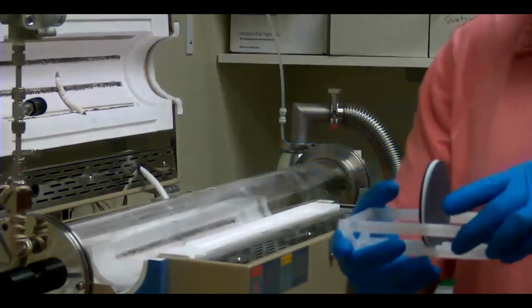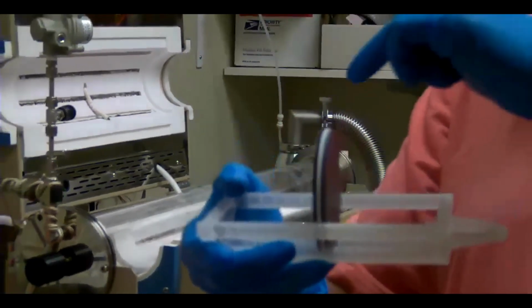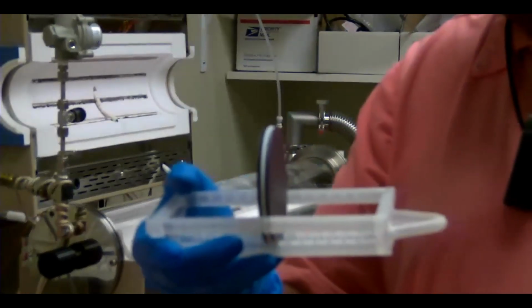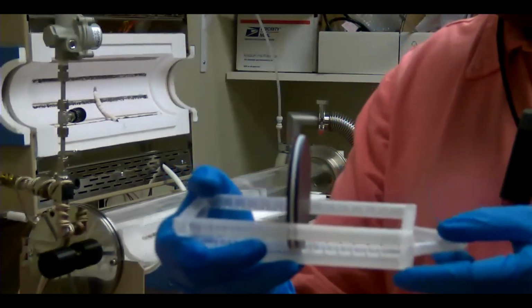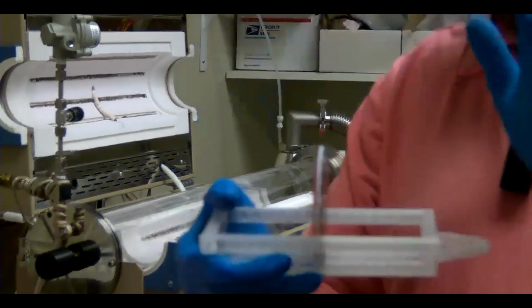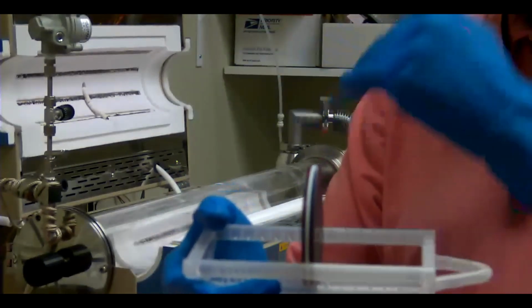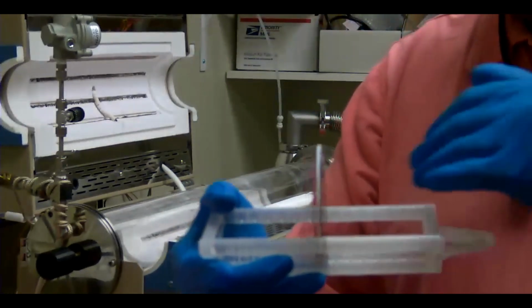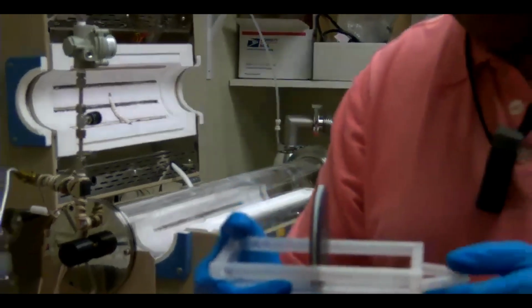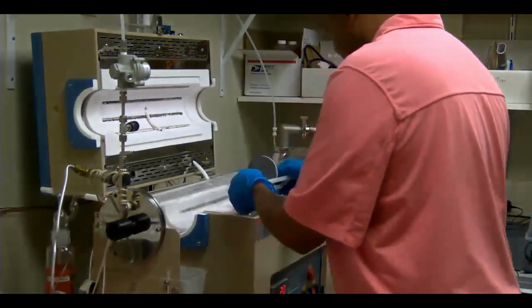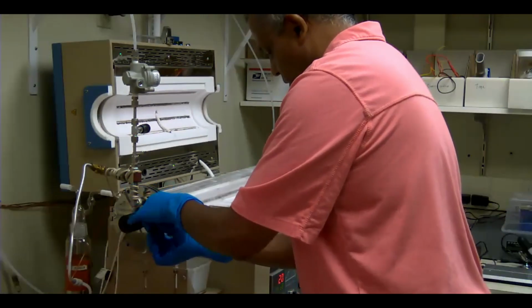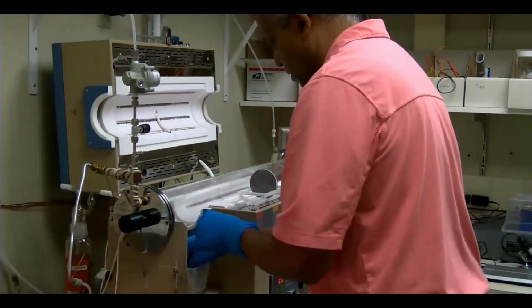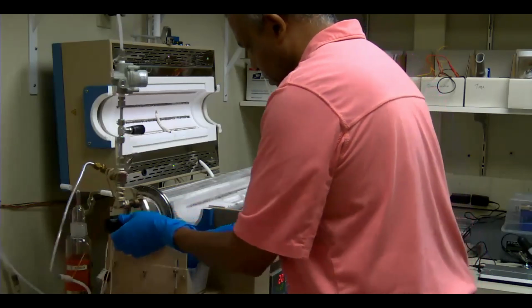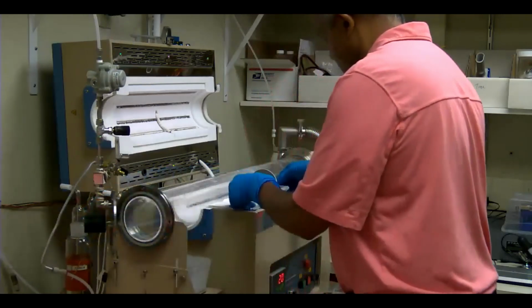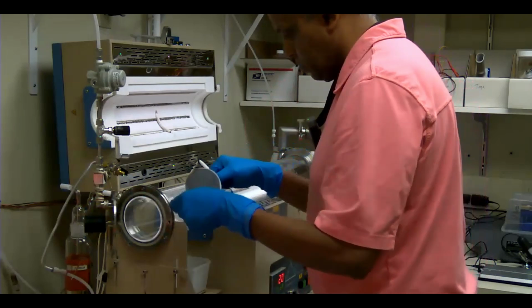Here is the structure. We have the ceramic that contains the boron oxide in the middle, silicon on either side. The doping side is facing the boron, and this is the back side, which we are not doping, but we will have to dope that too later because that's an N-type substrate. We're going to run this at atmospheric pressure, but not with air. I'm going to replace it with nitrogen because we don't want to oxidize the silicon.